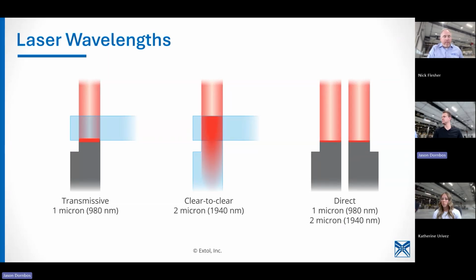Transmissive 1 micron is by far the most common that we see. We have done some direct laser, where essentially you are shooting both parts, getting them really, really hot, and pressing them together. When that happens, you generate a pretty substantial amount of smoke. For transmissive and clear to clear 2 micron,